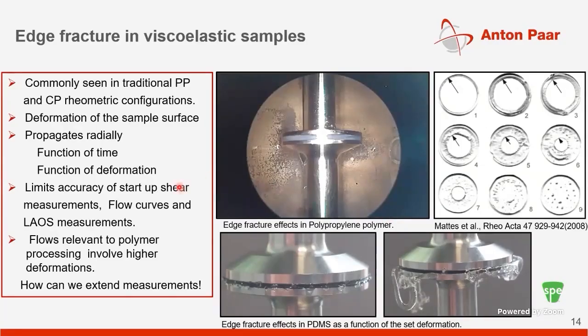Now, when you do non-linear characterization, which is of prime interest when working with polymers and polymer melts, especially at high strains or high deformations, typically a parallel plate configuration is used. You'll frequently encounter an instability in the flow, and here I'm showing you a video of what the manifestation of edge fracture looks like. This greatly affects the accuracy of your measurements, as this video hopefully shows, as you increase strains on a polymer melt.